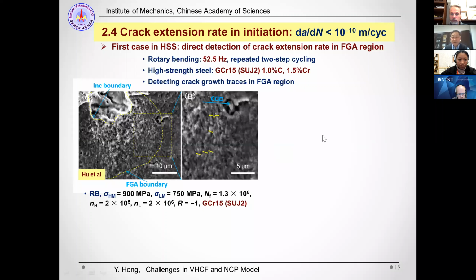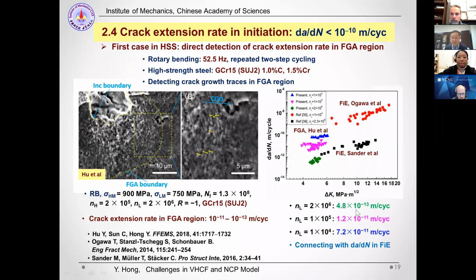The result shown here shows the rate is between 10^-11 and 10^-10 meter per cycle. And we are happy to see that the result here can be well connected with the growth data in the fisheye region outside the FGA, meaning that the initiation extension rates and the early growth stage crack rates, from the beginning to the early growth, can be well connected. This we are happy to see in the data trend.